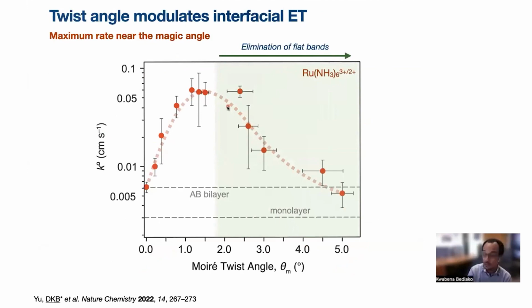But what is going on at these smaller angles, where we expect that you should still have flat bands, at least for these room temperature experiments? The bands in this regime should always be flat enough that we'd expect to see some effect. So what's going on there? And to understand that, we need to think a little bit about the actual structure of twisted bilayer graphene.